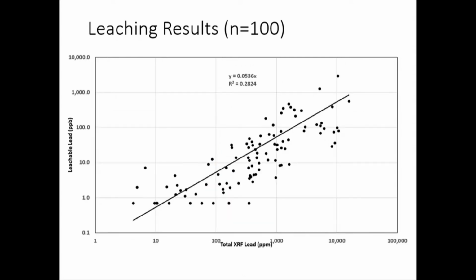So getting back to the scatter and my correlation coefficient. First, the total lead that you're measuring is with an XRF. Generally, obviously, we tried to do it on the interior of the pot, but sometimes the pots were too small. We had to do the exterior, where liquids are not in contact. Some of the pots were very variable and heterogeneous in our XRF measurements, and we took a median value. So how well that represents is another question.